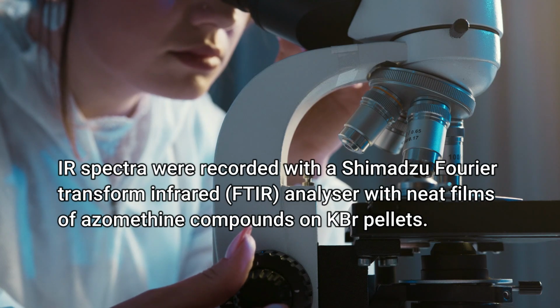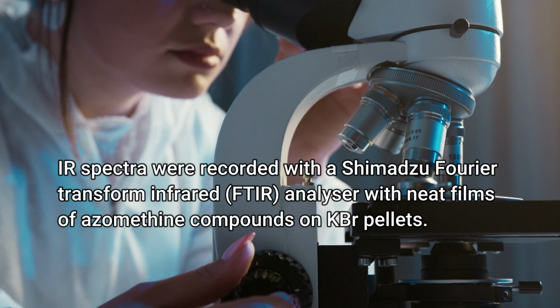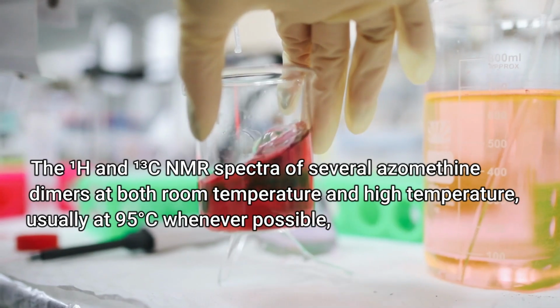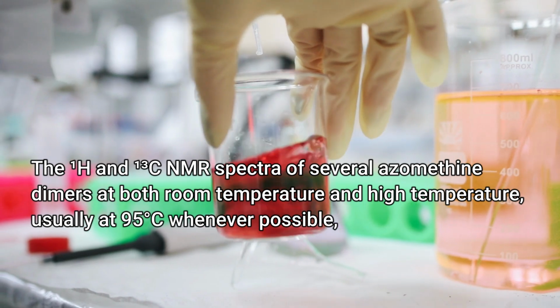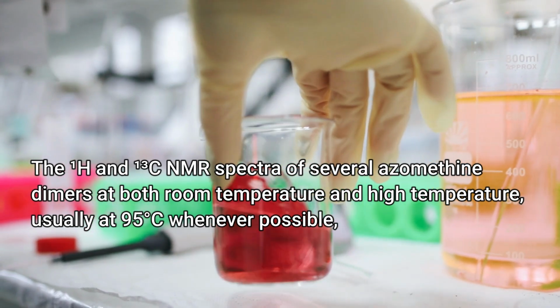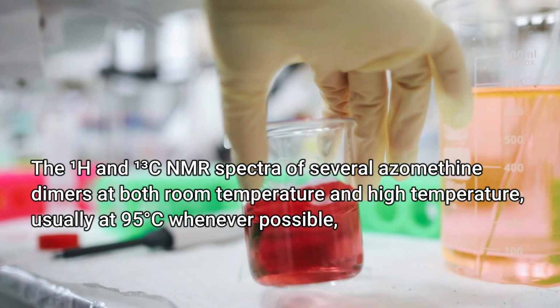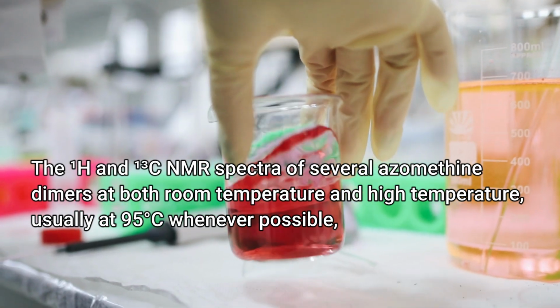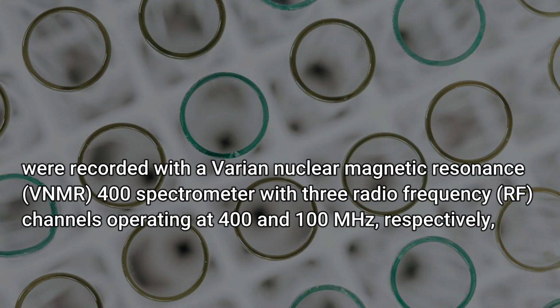IR spectra were recorded with a Shimadzu Fourier transform infrared (FTIR) analyzer with neat films of azomethine compounds on KBr pellets. The 1H and 13C NMR spectra of several azomethine dimers at both room temperature and high temperature, usually at 95 degrees Celsius whenever possible, were recorded with a Varian nuclear magnetic resonance (VNMR) 400 spectrometer with 3 radio frequency (RF) channels operating at 400 and 100 MHz respectively.